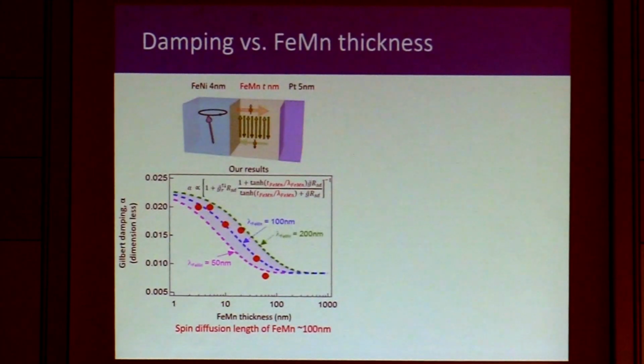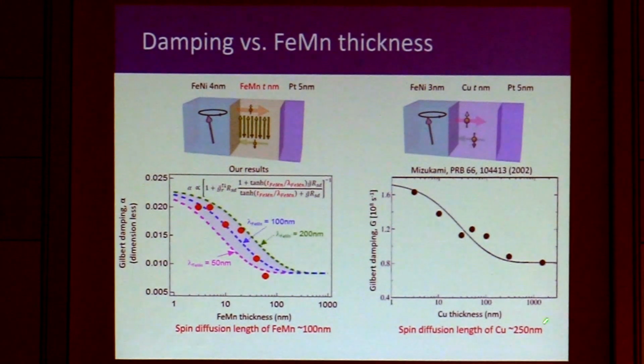First, we did a very similar experiment to the previous copper experiment. We put the iron manganese antiferromagnet and varied its thickness, and then we characterized the damping alpha. Again, damping decreases as we increase the iron manganese thickness. By using this equation, we can characterize the spin diffusion length of the iron manganese to be 100 nanometers. This is very similar to the previous work. This spin diffusion length seems to be very long, but we may be able to explain it by the spin current carried by spin fluctuation, spin waves or magnons.